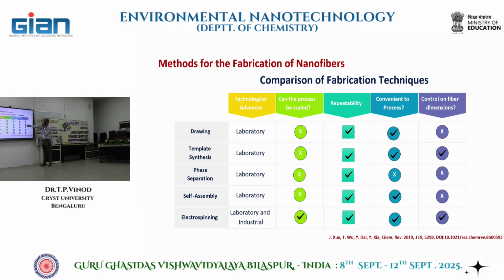You have very good control when you are using template synthesis. Just like that patterned opening, the diameter of the membrane depends on the opening size. In electrospinning also, you have very good control once you optimize the electrospinning conditions. Other places, for example phase separation, you are not directly controlling the size of the fiber, and self-assembly also is a self-regulated process, and we have less control over it.